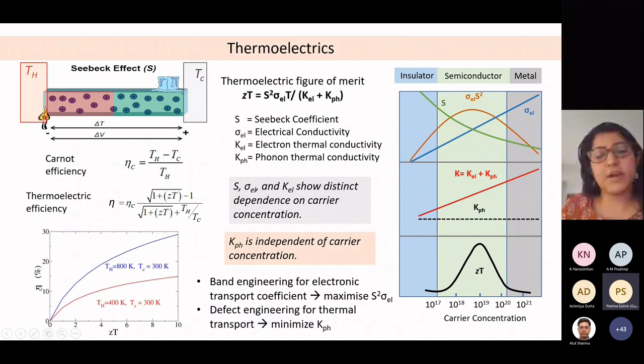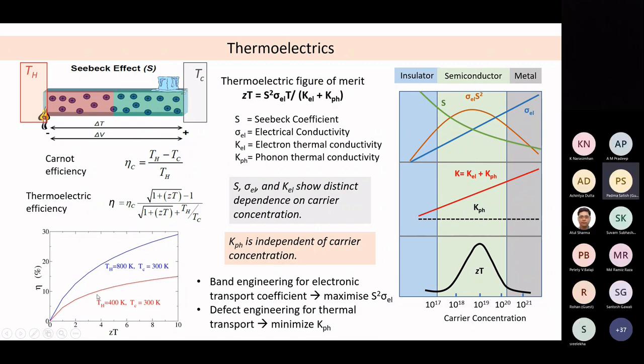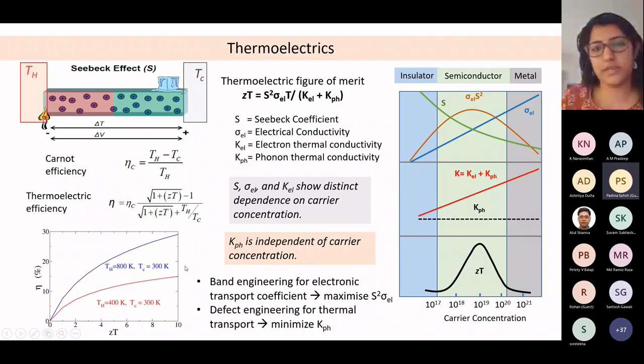And you can see, if I plot efficiency as a function of ZT, then in order to recover any meaningful efficiency, you need to have a ZT beyond 4 or so. But this is a very non-trivial problem, because if you try to maximize this particular quantity, the power factor, A squared sigma, which involves the Seebeck coefficient and electrical conductivity, then you also get this particular kappa_el in the denominator, which shows a similar proportionality with sigma_el.